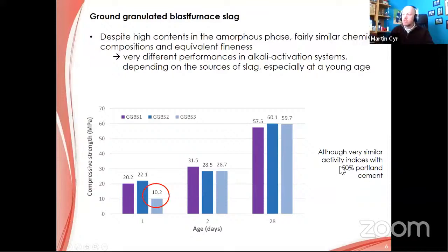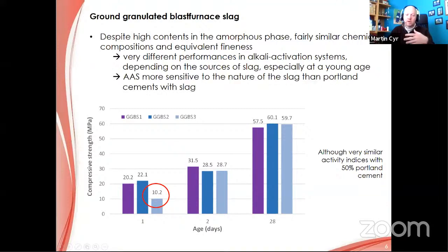Although we have very similar reactivity with Portland cement, what we can say, and it's not only for alkali activated materials, but it is also true for binders containing a lot of GGBS, supersulfated cement and other kinds of cement, is that these materials are much more sensitive to the nature of the slag itself than Portland cement will be. So we have to take care of this kind of thing and study, as was said earlier, for a particular precursor material, we have to make sure that it will work correctly and make some tests to make sure that it will work.